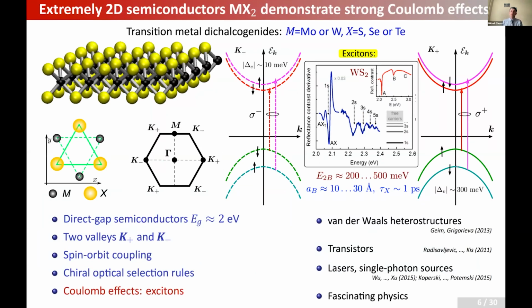Because of the low symmetry of these materials, the threefold rotation axis and the lack of an inversion center, the optical transitions are chiral, in the sense that light of a given helicity induces transitions only at a given valley. Say, sigma plus polarized, right-handed light induces transitions only in the vicinity of the K plus point of the Brillouin zone, while sigma minus polarized light induces transitions in the vicinity of the K minus point. This will be important for the fine structure of excitons. I will not go into much detail on how these materials are particularly attractive and interesting.